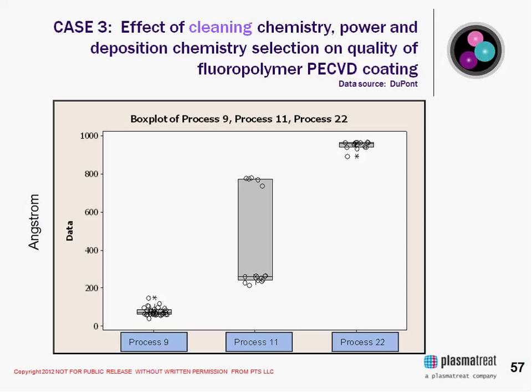Also the wet chemistry phase, from what I understand, was a very long process. And it's not as controlled as when working in a plasma. So the use of plasma for working with a lot of silanes is being more adopted, and there's many different silanes that we can introduce via plasma chemistry and control the properties in a very quick process. That process is 3 minutes.